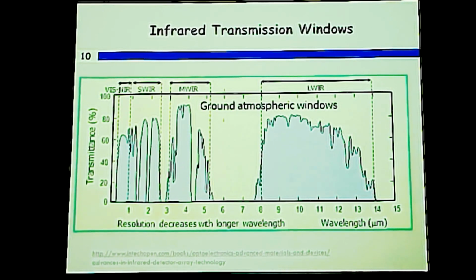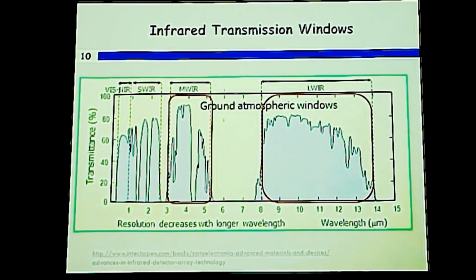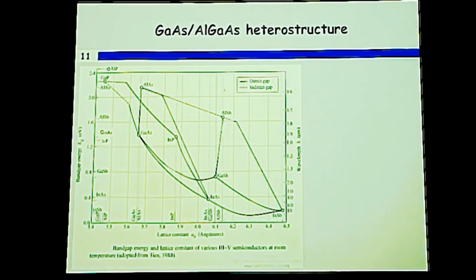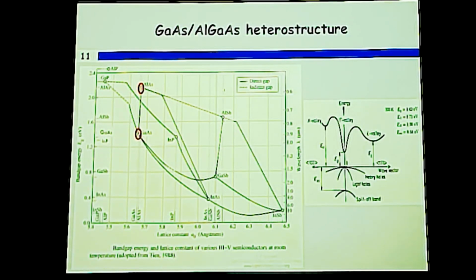There are certain spectral bands in infrared that are more important than others. 3 to 5 is one band, and 8 to 15 is another one. And we are primarily interested in the 3 to 5 band because the US Army is interested in detectors in this band, and we get support for our research from the US Army. And we are using mostly III-V semiconductors, gallium arsenide and aluminum gallium arsenide heterostructures, mostly because there is very good lattice matching between these two material systems, and that is very important to make large scale focal plane arrays, with a large number of pixels. And also we use p-type, because the split-off band energy gap is close to the mid-infrared range that we are looking for.